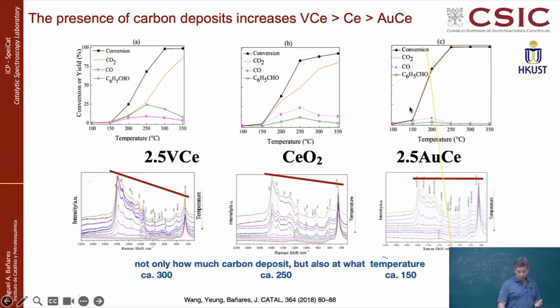But in the case of gold, basically what happens is the conversion is much better, and the yield to CO2 is pretty much the same line as the conversion, almost total selectivity to carbon dioxide, with a little bit of partial oxidation, but negligible. So gold makes it an excellent combustion catalyst, and vanadium makes it more for partial oxidation.